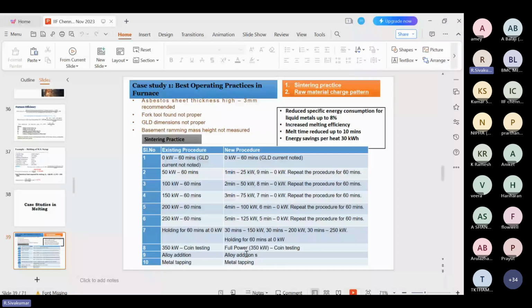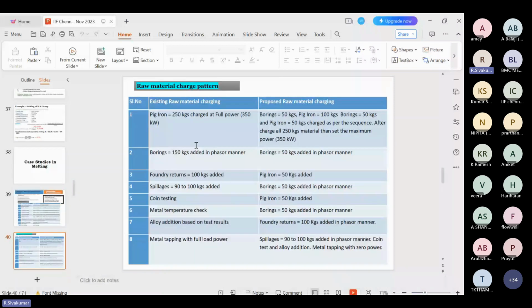And this is the raw material charging pattern. The same raw material only, we change the pattern of loading into the furnace. In the existing practice, pig iron 250 kgs is charged at full power, that is 350 kilowatt. In the proposed method, initially 50 kgs of boring was poured at the lining bottom, and again 100 kgs of pig iron was added. Next 50 kgs of borings are added, and again 50 kgs of pig iron is added in a sequential manner. First boring, second pig iron, third boring, fourth pig iron, in such a way. After charging all the 250 kgs of material, then set the maximum power to 350 kilowatt.